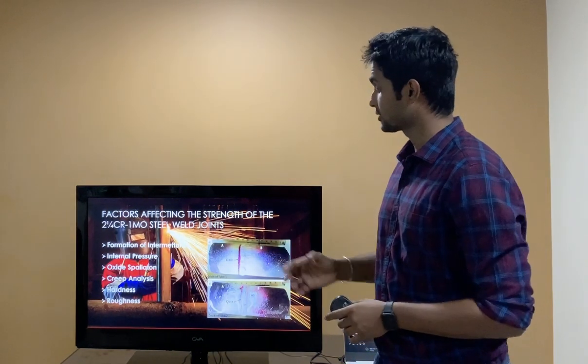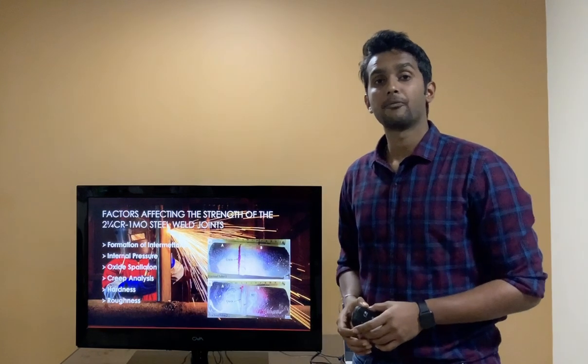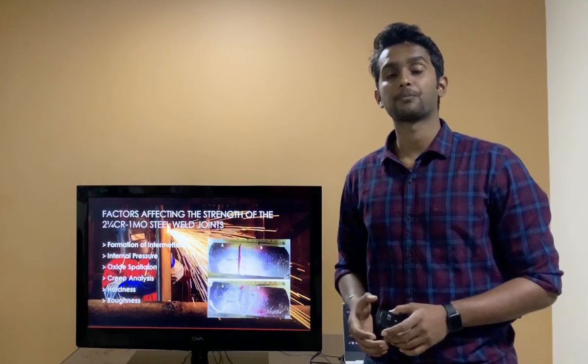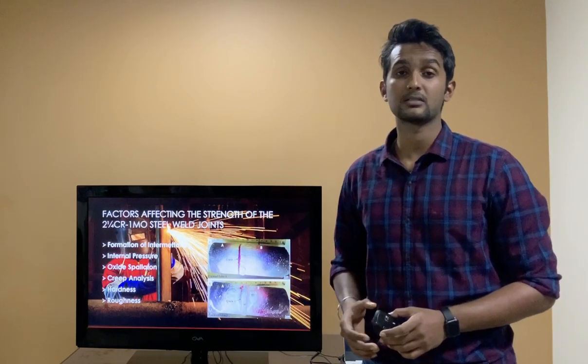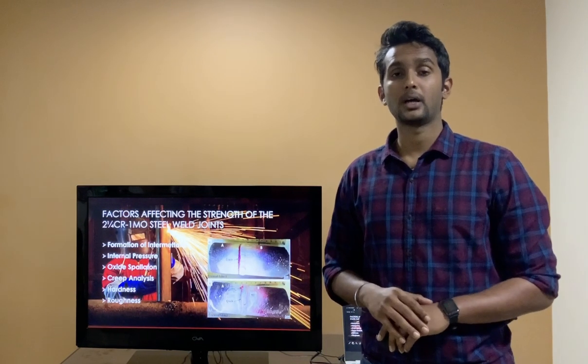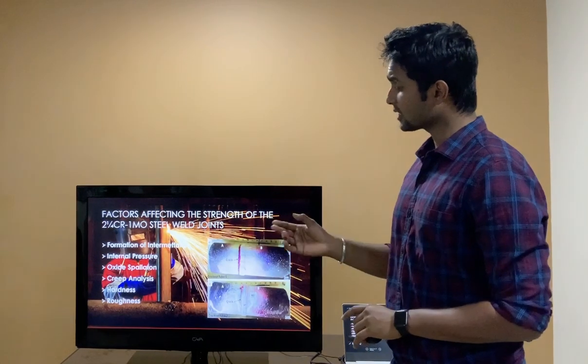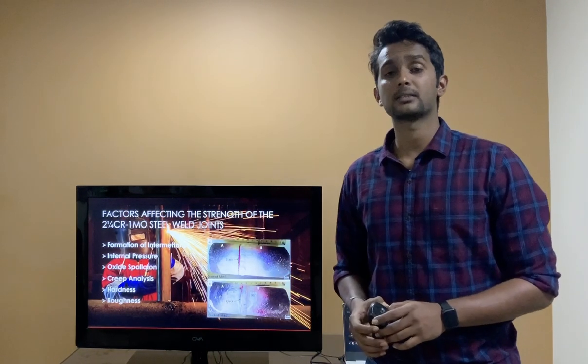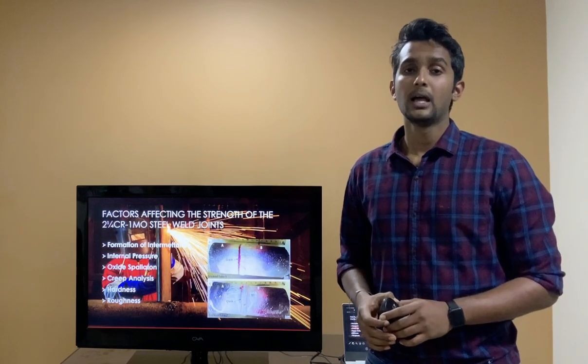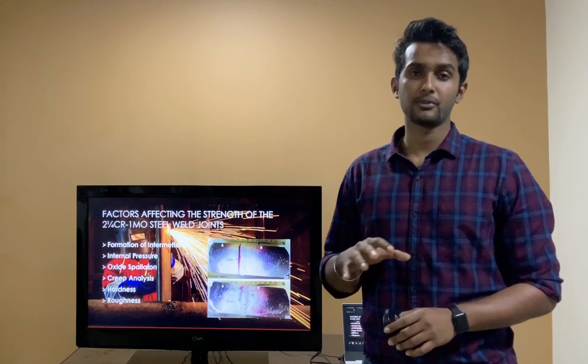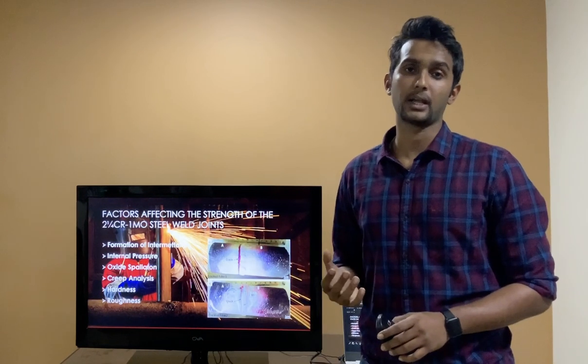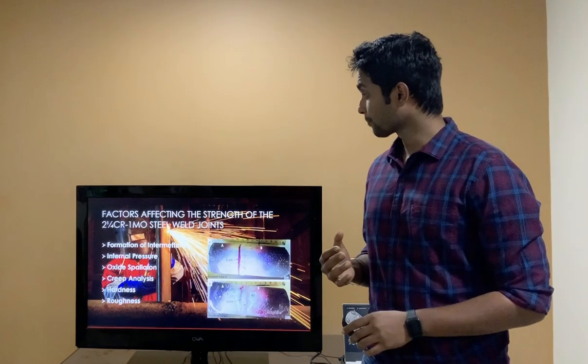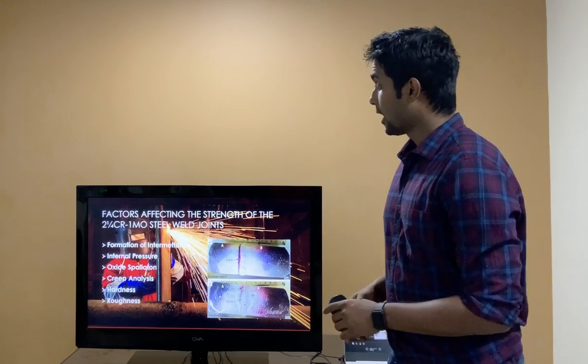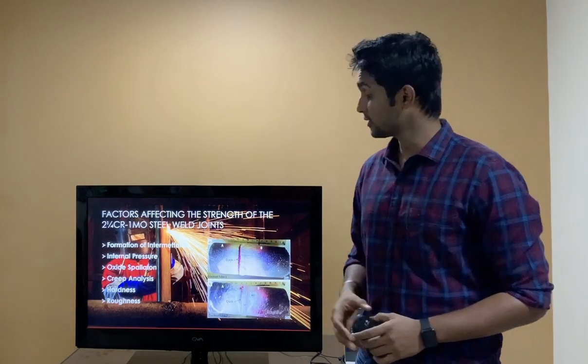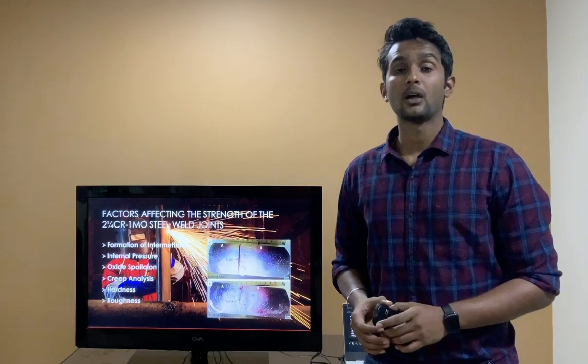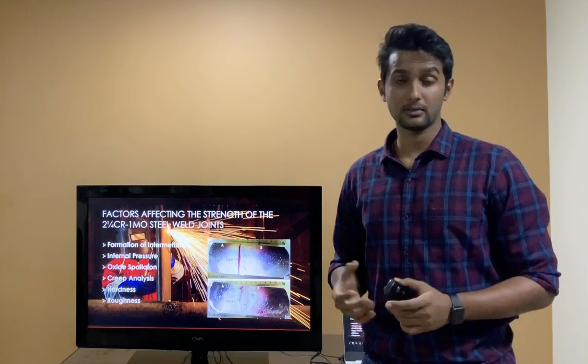Next comes the oxide spallation. We do have the problem of experiencing the formation of oxide layers inside the boiler tubes due to the incorrect weld parameters. Next comes the creep analysis. Creep formation is a nightmare for the weld joints, where when a higher load is applied on top of the weld joints, they tend to break, or are more susceptible to failure. Next comes the hardness. Hardness and roughness are nothing but how we measure the strength of the weld